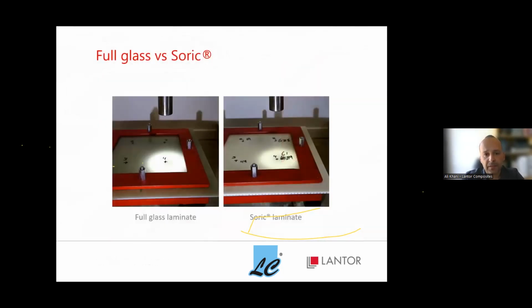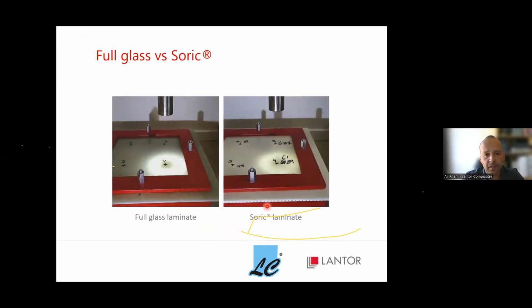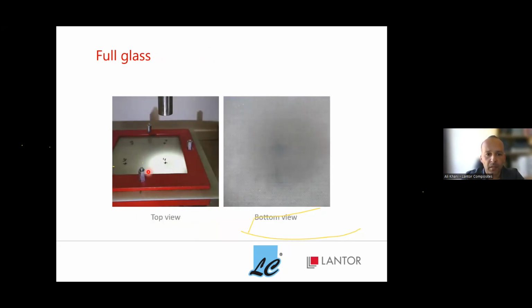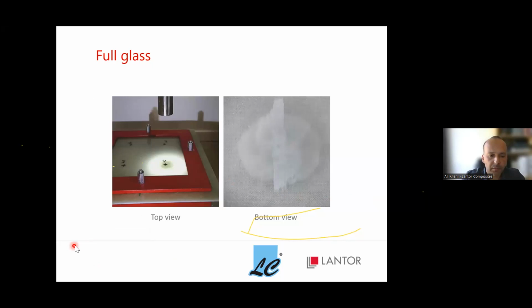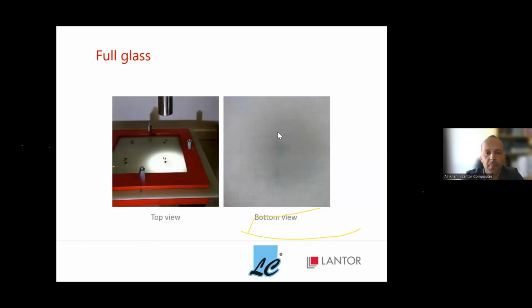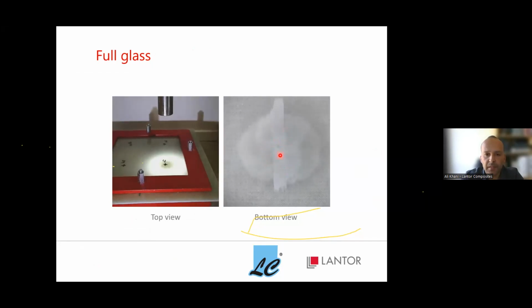I have some impact studies we have done for two laminates, a full glass laminate and a sandwich laminate, a Soric laminate. These two laminates have the same bending stiffness. The sandwich laminate is designed such that the bending stiffness is exactly the same as the full glass laminate. And you can see here the impact tests. This is the top view, and this is the bottom view of the full glass laminate. Let me check if I can play it again. Yes, so this is the bottom view, and you can see this bottom glass layer is broken.